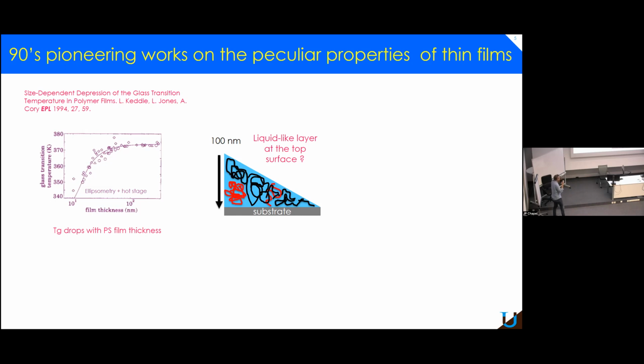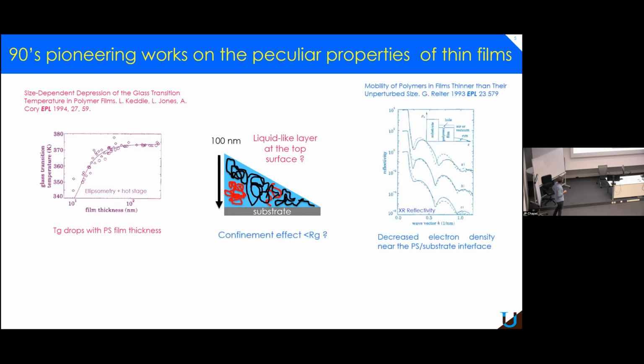And so the idea at that time was that maybe there is a liquid-like layer on top, and this basically was able to reduce the glass transition. Pretty much at the same time, Gunther Reiter also made a very interesting experiment using X-ray reflectivity. And in his experiment, he showed that basically when the polymer layer is confined within a couple of radius of gyration, the density near the substrate is changing.